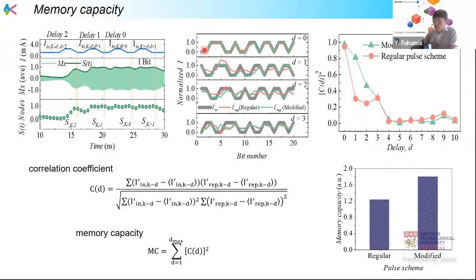Of course, in the case of no delay, we can reproduce the input signal from the output. In the case of D1, with the regular pulse, we can see a good fitting like this. But when we increase the delay, it's getting hard to reproduce. Then from the correlation coefficient, we can estimate the memory capacity of this spin Hall oscillator.